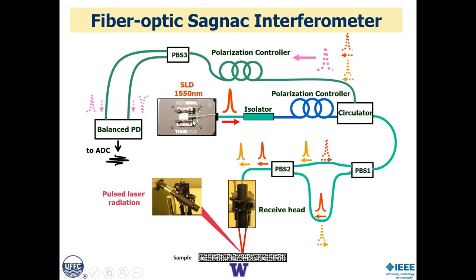So you have a broadband light source, which launches wave packets. Through polarization tricks, you can then split this into two wave packets. These are coherent packets, but they're now split into two optical paths, one with a delay, so that when you come to the delivery system to the surface, you have two wave packets delayed by a fixed amount, typically on the order of 10 or 20 nanoseconds.